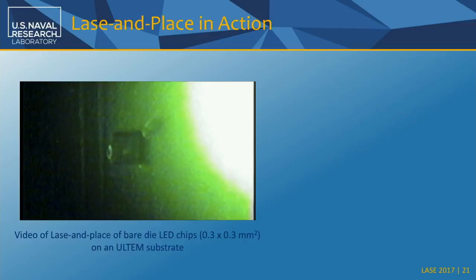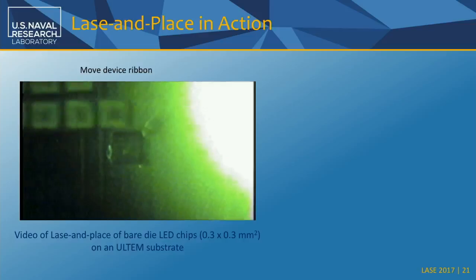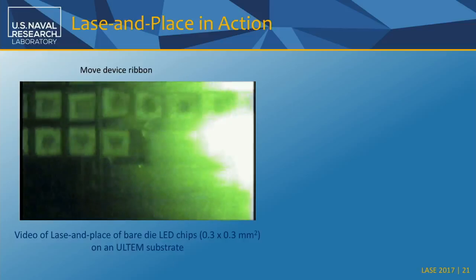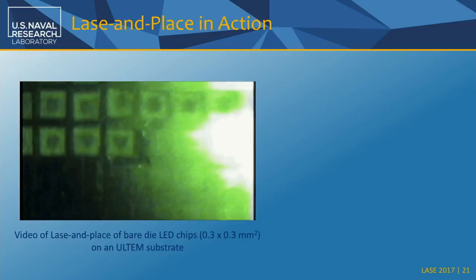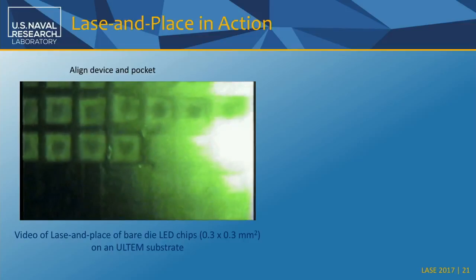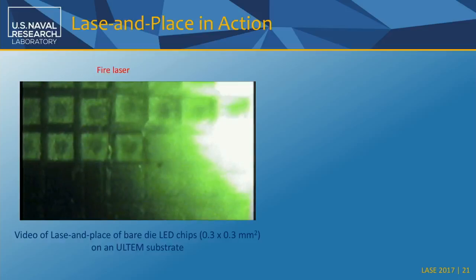And here on the left is an old video that we took when we were setting up the process. What you see here is a pocket. This is polyimide, a substrate that we're using. It ablates very well at 355, so we can make a receiving pocket. And this is what the operator is seeing on the monitor, and you can see it moving the donor substrate, and each one of these is a device that is being attached with a resist, with a polymer layer.